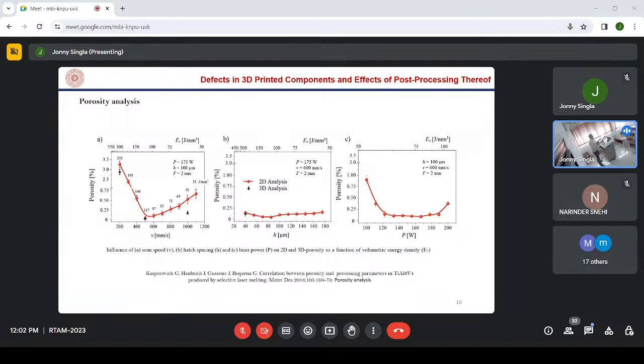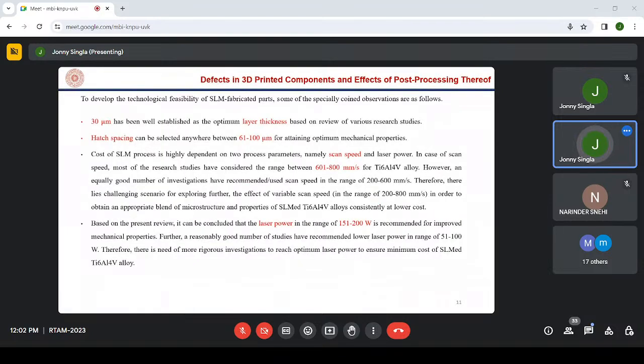So to keep the porosity to the minimum level, if you keep these four parameters at this level, then your product will be almost a dense structure. So if you summarize, these are what I have given in red. Layer thickness 30 micrometer, hatch spacing 60 to 100 micrometer, and then scan speed 600 to 800 mm per second, and laser power 151 to 200 watt.